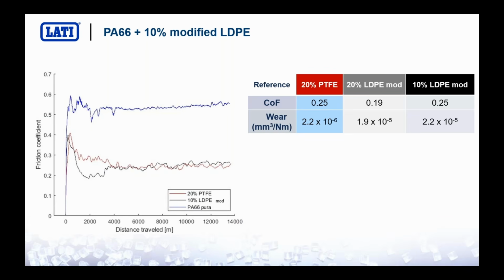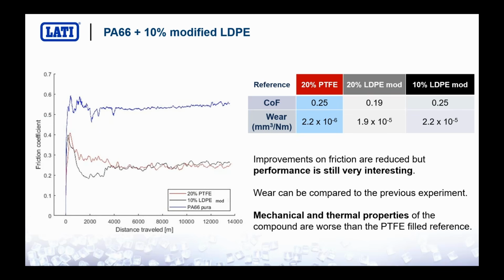So that's the main reason why this kind of solution cannot be proposed to replace one-to-one a polyamide 66 plus PTFE. So we tried also to halve the percentage of the LDPE in order to check the tribological behavior, and we obtained also in this case very good results in terms of friction coefficient, which is more or less comparable, also from a curve point of view, with the PTFE, while the wear remains too high. But also in this case, adding 10% of LDPE, the mechanical and the thermal properties of this kind of compounds are really low compared to a polyamide 66 plus PTFE.